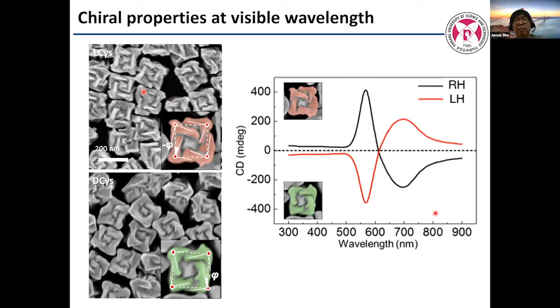And this is optical measurement. It's a left-handed chiral nanoparticle and a right-handed chiral nanoparticle, so they have exactly mirrored CD responses in visible frequency. This is not active, so we cannot change this peak in real time, but we have many different growing conditions, so we can tune from 400 to 700, with many different particles.